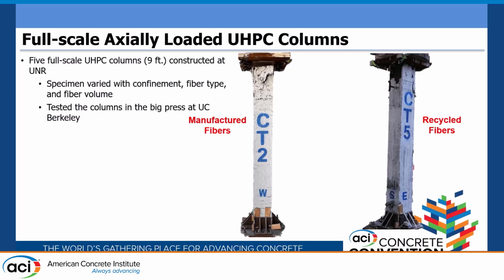Can we go from 2% fiber to 1% fiber? Because it's just pure axial, right? So technically the fibers aren't going to be too crucial. So we shipped this column. I mixed this in our yard with a high shear mixer. We developed like 5 per batch, so it took a lot of time. I got help from my colleague at that time. We shipped these columns and went to UC Berkeley with the big press machine.